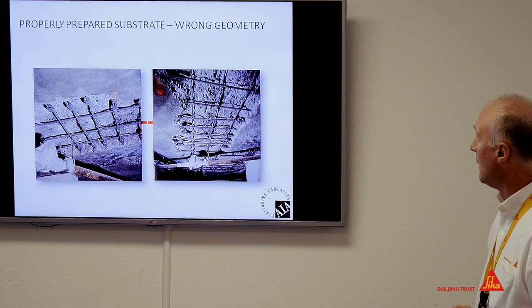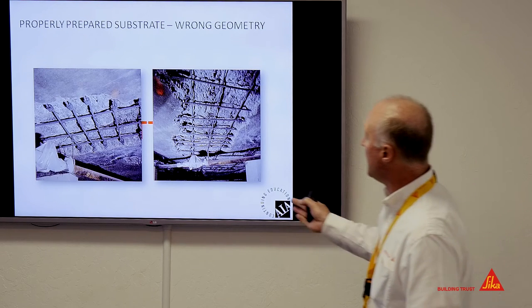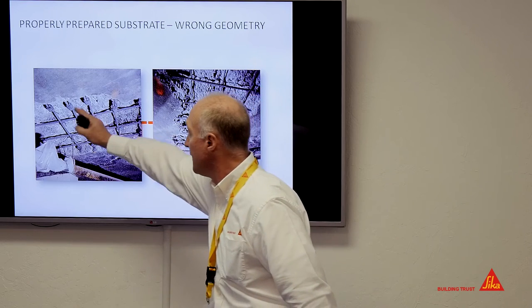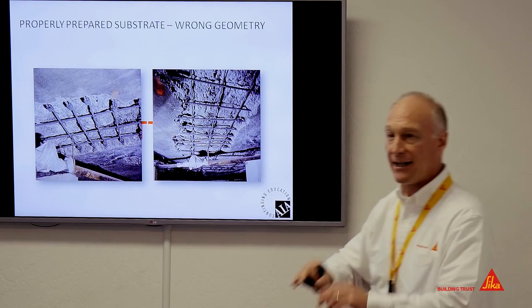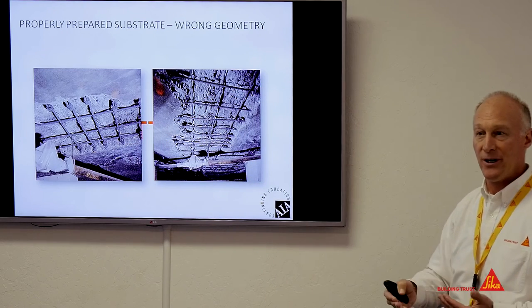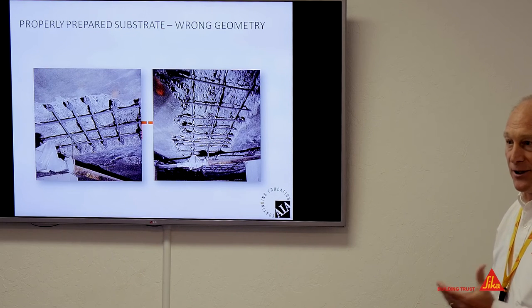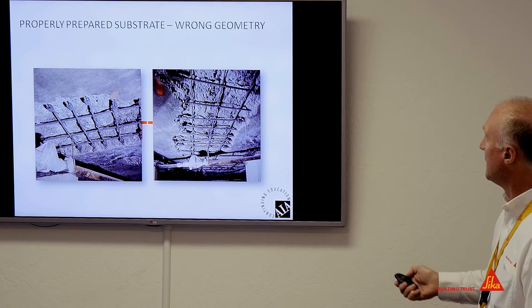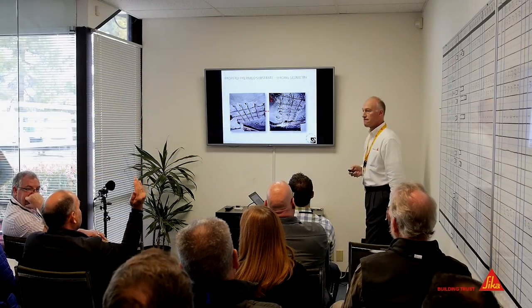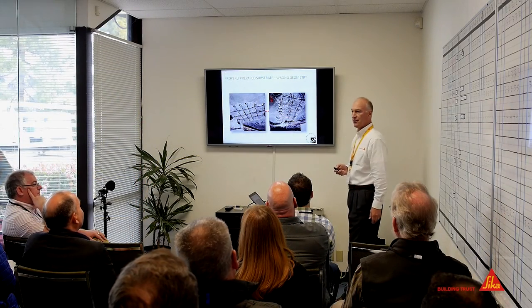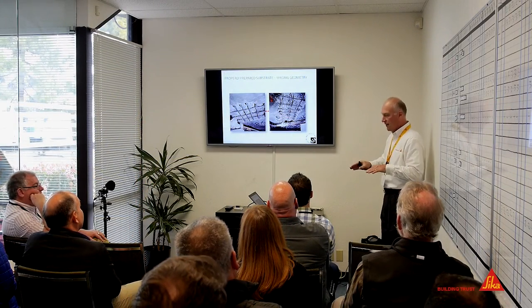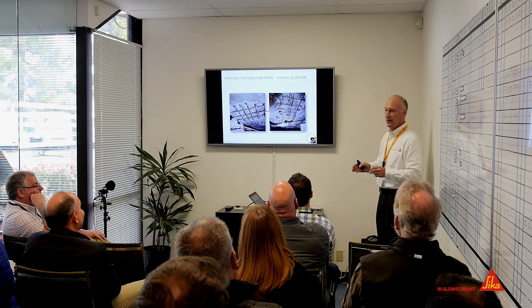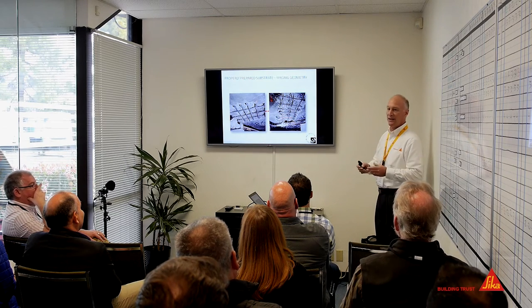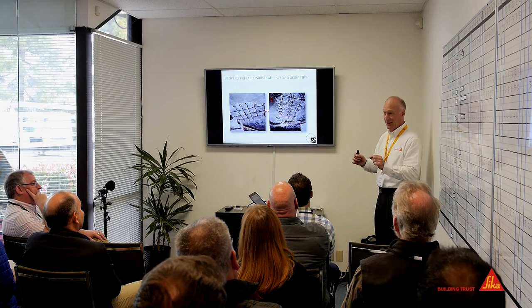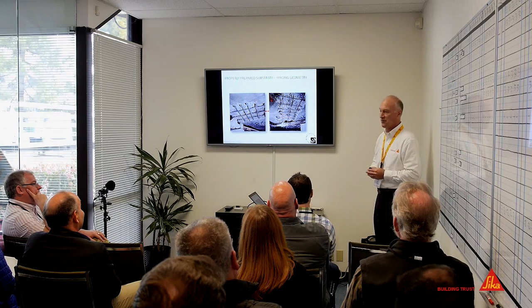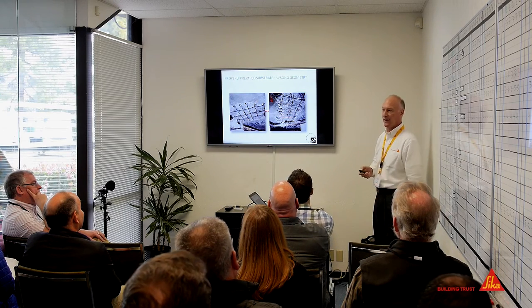Okay, so this is an area, the geometry, that's not ideal. I'd like to see a saw cut around the perimeter, and again, a reasonably simple geometry. Could you do a little dovetail on the saw cut or just straight? Just straight is fine. You don't need to try to cut that in, you'll get really good adhesion of the repair material. Ideally, you'd like to roughen up the saw cut a little bit. Reality is, it doesn't really get done, but you get good adhesion with that anyway.